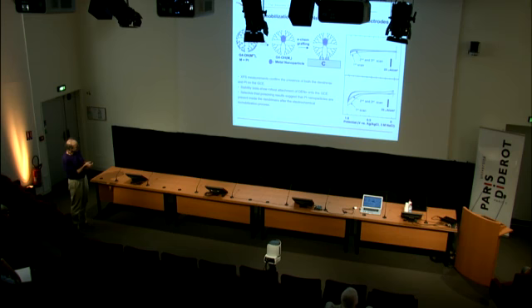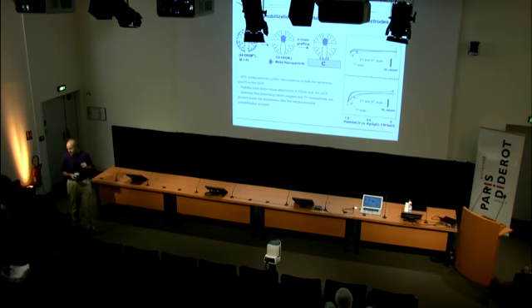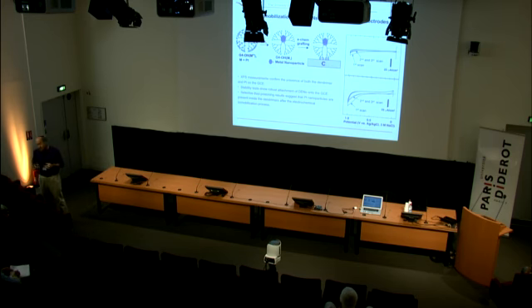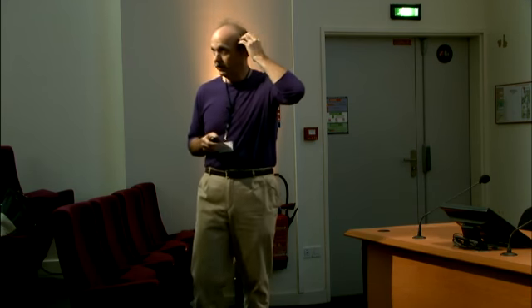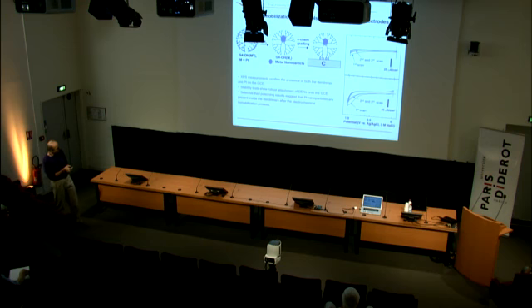Now I've added borohydride. The particle has formed under the influence of the reducing agent. And now I'm going to graft that onto a glassy carbon electrode. Now, a powerful aspect of this technique is that before I graft this particle onto the surface, I can take it and characterize it, by whatever favorite technique you have: dynamic light scattering, TEM, XAFS. These particles are small, 40 to 200 atoms, so they're too small to do normal X-ray diffraction. But we do a technique at the synchrotron called X-ray diffraction pair distribution function. And so with a synchrotron, we can actually do X-ray diffraction on these. Not so easy as just doing powder diffraction in your own chemistry department, but possible.